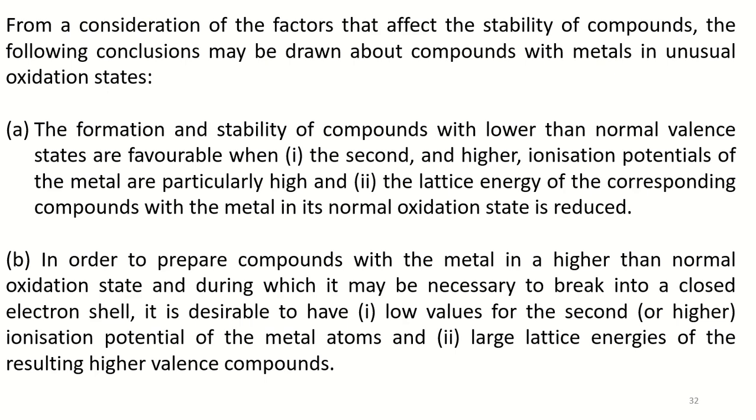As an example of these trends, calculations for alkali and alkaline earth metal monohalides show that while all are unstable relative to the dihalides, the enthalpy of disproportionation is least in each case for the iodide. On the other hand, the higher valence halogen compounds of group 1 elements are most likely to occur with cesium and the copper subgroup in combination with fluorine.